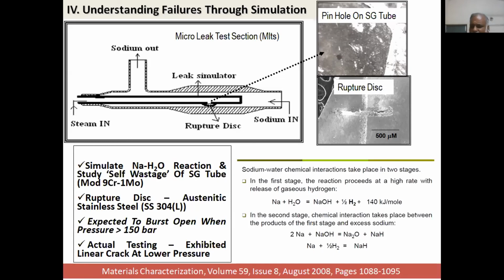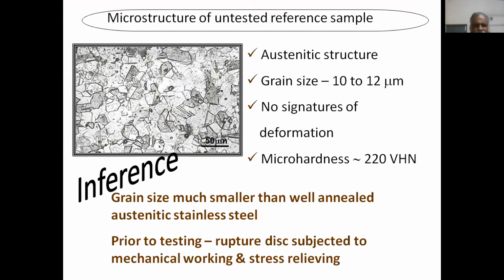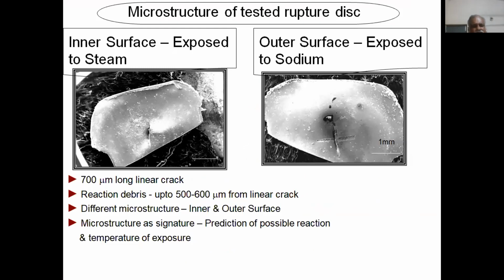The starting material is very simple, 10 to 12 micron grain size, very good austenitic stainless steel. No signatures of deformation, hardness 220 VHN, a typical microstructure of an austenitic stainless steel. Grains are very fine prior to testing. The mechanical rupture test was done. The piece which was given to me after the testing, we examined on two sides.